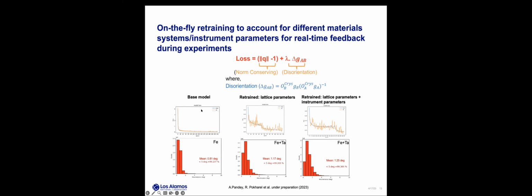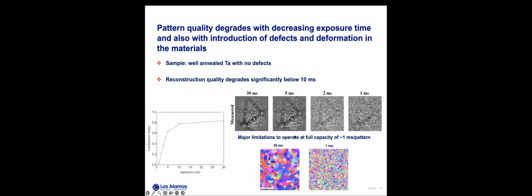And so the idea behind this on-the-fly retraining approach is to develop a model architecture and train a base model before conducting any experiments. And then using a small number of experimental patterns, you can quickly retrain some of the model parameters on the fly to account for changes in the material systems or instrument parameters or other factors. And this enables faster microstructure reconstruction for us to provide feedback during experiments.